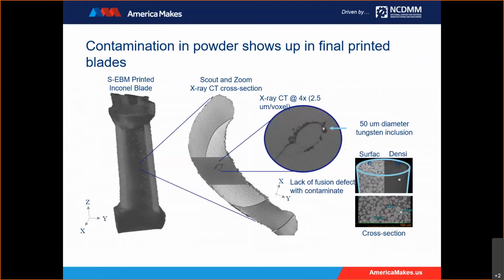Now let's take a look at some case studies. At ZEISS, we work with researchers at Oak Ridge National Lab to qualify the parts using X-ray CT. In this project, we're looking primarily for cracks in E-beam printed Inconel blades when we found some tungsten inclusions. And it's pretty easy to pick them up because they have a much higher density than the bulk Inconel.